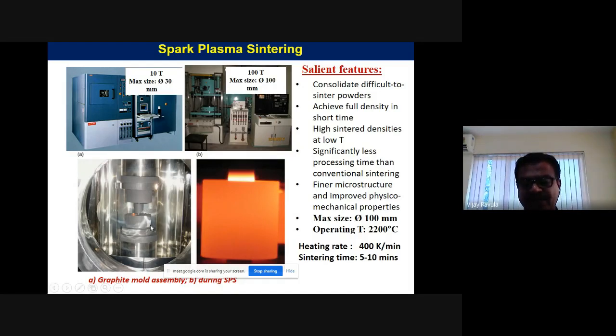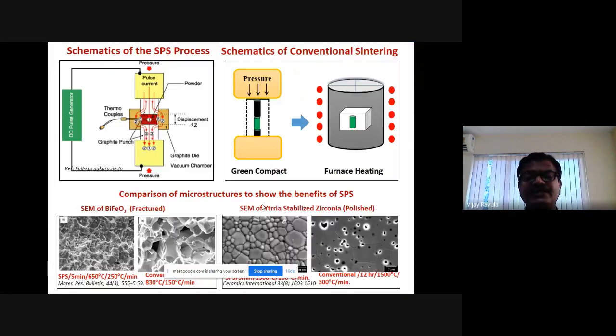And these are the graphite dies, where the material is put in the die with punches. When the high current is passed, you can see the red hot die, which is actually at temperature. That's the picture. In the SPS process, you pass very high current in pulses, and because there is a gap from particle to particle, that creates a spark. Also graphite is a good conductor, so there is Joule heating taking place because of the high current, I squared R is the heat generated. That's why the temperature rises very fast. Then you simultaneously apply pressure, and they get consolidated.